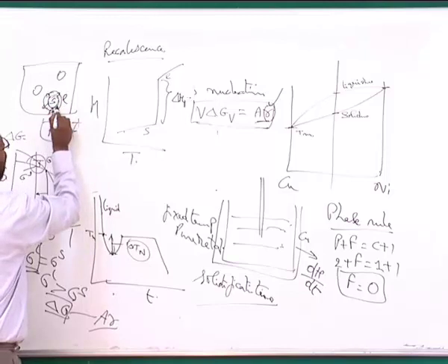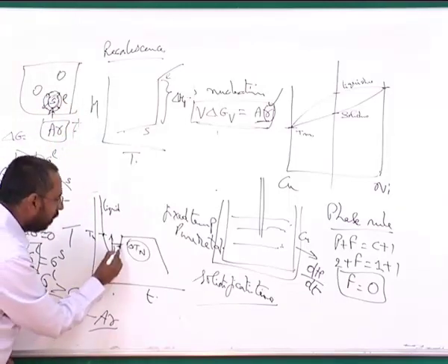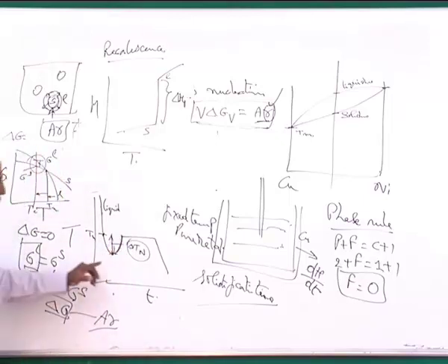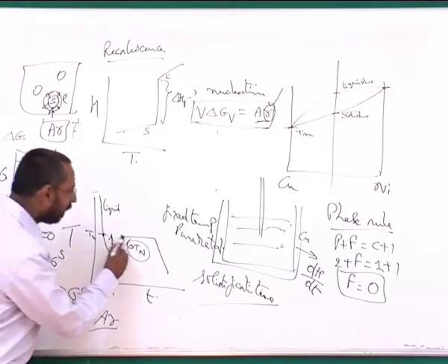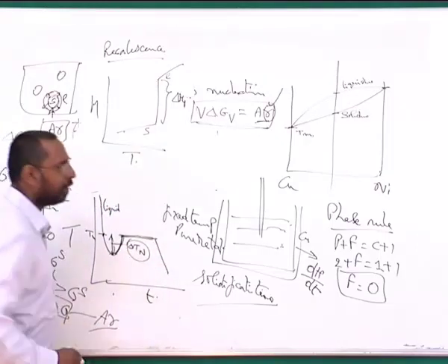So as a result, the surrounding liquid gets heated up, and you can see this particular thing happens. This is what we call recalescence, where the temperature rises and finally reaches this constant temperature. Why does it reach a constant temperature? Ultimately because this has to be satisfied.